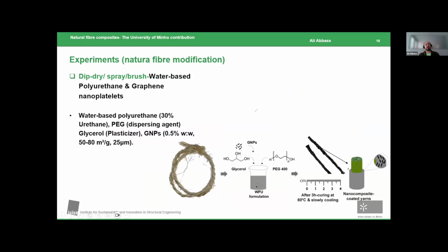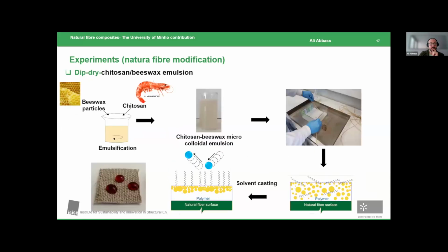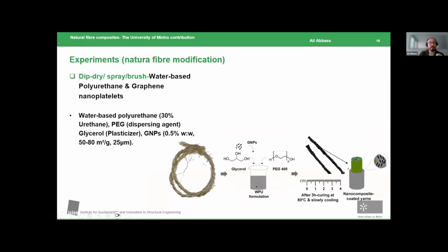So now moving to the last protocol, and this is the winning candidate of the entire campaign. So we moved from bio-based... sorry, I forgot to mention that the tensile behavior, of course, with all the other characterization tools we've carried on, was good, but it didn't eliminate this low initial stiffness fully. So this is just to keep in mind why we moved to this protocol. So this final protocol comprises the use of a water-based polyurethane, very low resin content. We're talking about 30% resin content, and the rest is just water byproduct.